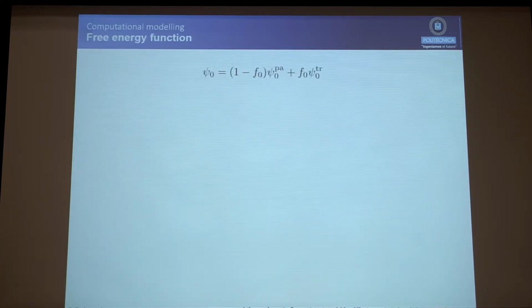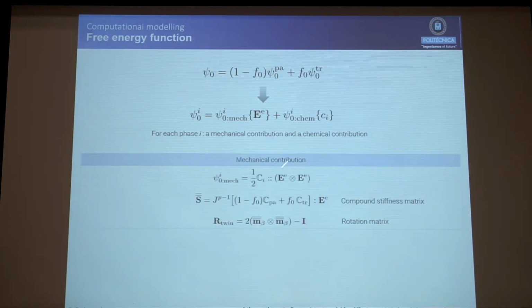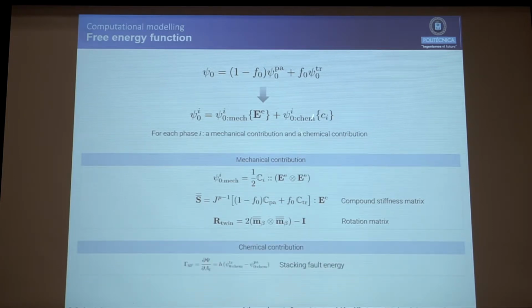So the Helmholtz free energy of the system will be a combination of the parent phase free energy and the transform phase free energy, scaled by the fraction that we have of each of the phases. Each of these Helmholtz free energies, of parent and transform, will have a combination of mechanical free energy and chemical free energy. The mechanical free energy is coming solely from the elastic energy of the material, which is loaded. And here we are also taking into account the elastic stiffness of the parent phase and the transform phase. The chemical contribution to the Helmholtz free energy is basically dominated by the stacking fault energy, which is the difference between the free energy of the twin system and the previous parent phase. And it's a concept that metallurgists use for their models, actually, more than continuum modelers.